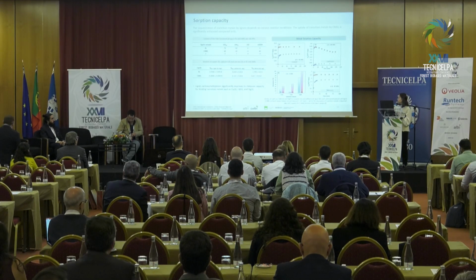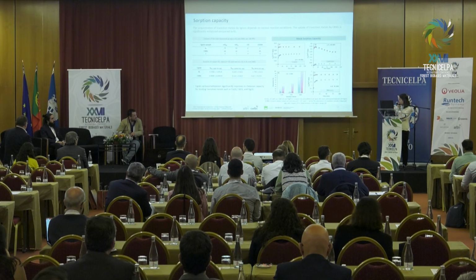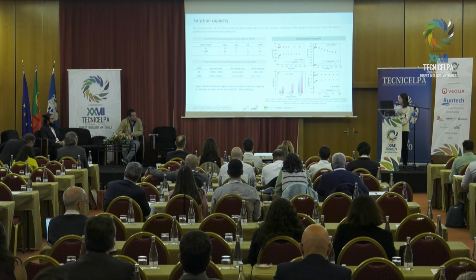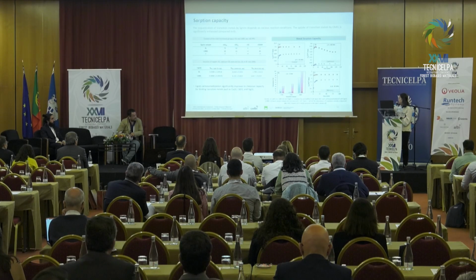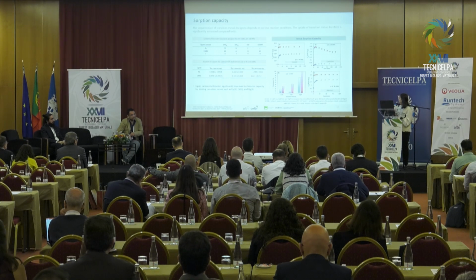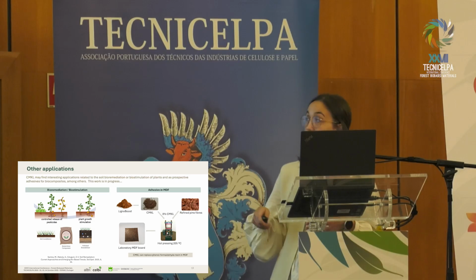We observed that, of course, kraft lignin has some carbonyl groups, some hydroxyl groups, and they have some sorption capacity, but this modification strongly improves the chelation capacity. For example, for copper and for mercury, we observed that this modification resulted in higher uptakes, and the equilibrium was attained in a shorter time. So you have a faster equilibrium time for the carboxymethylated kraft lignin. Regarding cadmium, the uptake for the modified kraft lignin was 7 times higher than for the unmodified lignin, but it takes some time to reach equilibrium.